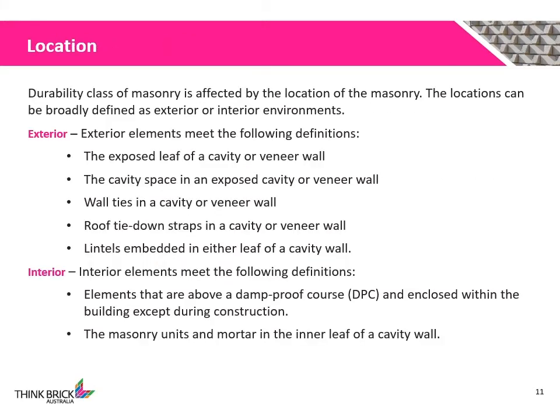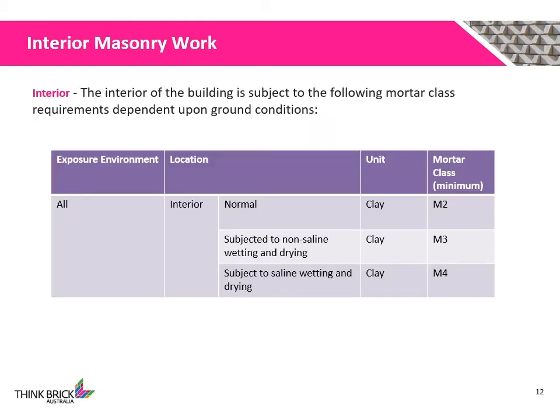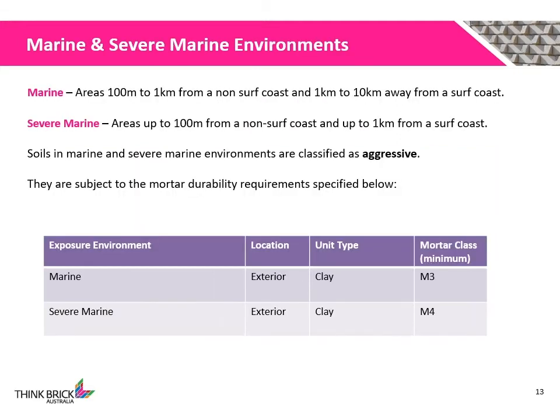The location of the masonry will also affect the mortar durability requirements. Location can be broadly defined as exterior or interior environments. Exterior and interior elements must meet the definitions as shown below. Interior masonry work is subject to mortar class requirements dependent upon ground conditions, and the minimum mortar classes for those ground conditions are listed below. Marine environments are defined as areas that are 100 m to 1 km from a non-surf coast, and 1 km to 10 km from a surf coast. M3 mortar shall be used as a minimum for these environments.